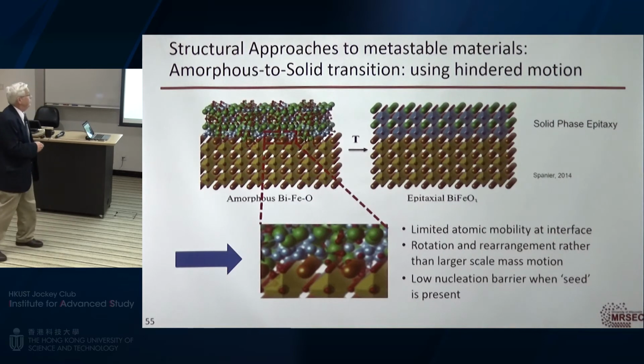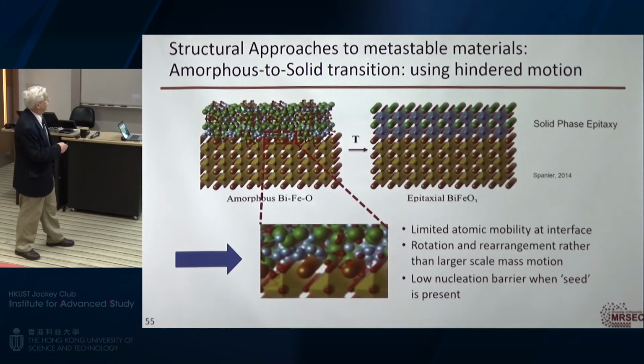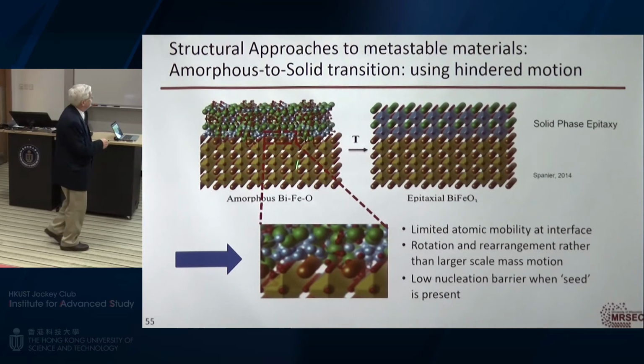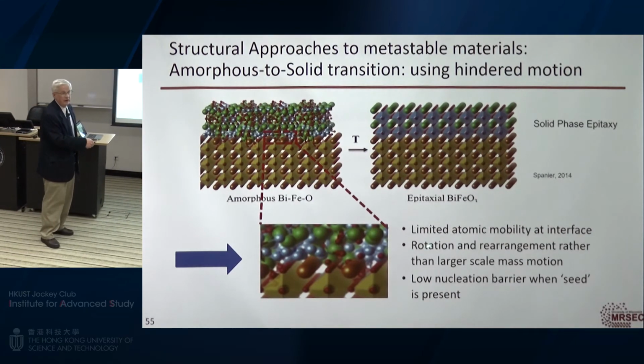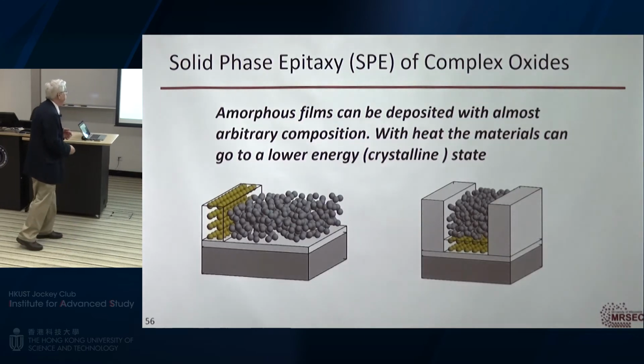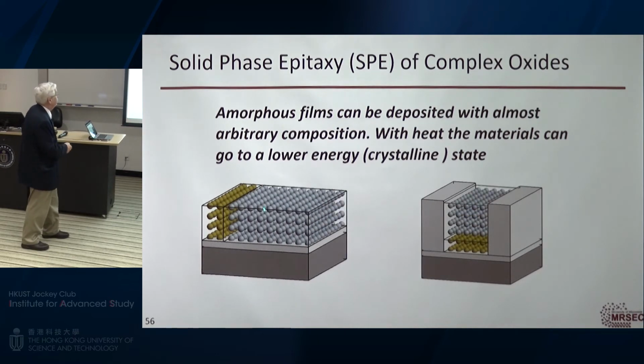And so there are competing forces here. One is, do I nucleate a new phase in the bulk of this material, or does it grow from the surface? Just as we're using the limited surface mobility to create the metastable semiconductor alloy, at this interface there's very little atomic mobility for atoms to move around. At best, some of these atoms can rotate around and maybe move one or two sites if you heat it up at low temperatures, and that's just enough for it to reorder. So what we can do is deposit amorphous materials of arbitrary composition and then heat it up, and hopefully it will reorder.